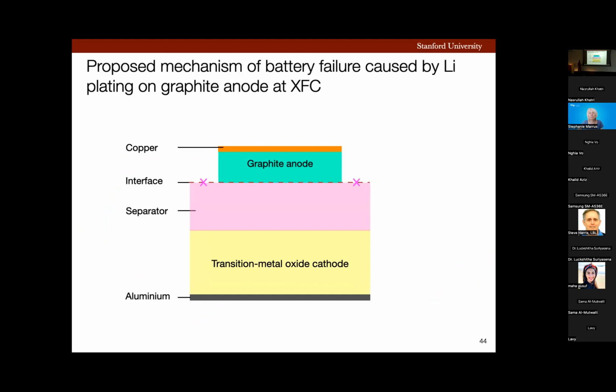Lithium most probably initiated at this interface, but then it grows towards the copper current collector, towards the center of the graphite anode, and in the separator in the form of these deposits with different morphology at 6C. Whereas lithium near the current collector has a way to intercalate into the graphite, leaving behind these irreversibly plated or dead lithium deposits, which cause capacity fade of the battery.